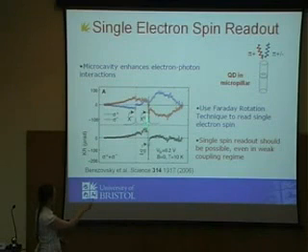In fact, this was achieved by Berezovsky and co-workers in this paper in 2006. You can see here's the energy where the quantum dot is. It's quite difficult to explain exactly what's being plotted here, but you measure the rotation in microradians of the probe pulse as it passes through this quantum dot transition, and they reached about 200 microradians. This is quite a low rotation, but they measured a very low quality cavity. They didn't have any lateral patterning, and the Q factor was about 50, whereas the kind of structures we're looking at have Q factors of about 5,000.